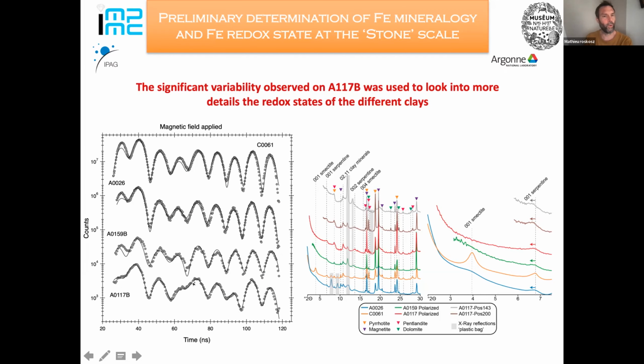And so we were very happy to see that this grain, or this position on this grain, was probably documenting clay minerals with a large amount of serpentine and a very low amount of smectites, which allowed us to look at the redox state of serpentine as compared to smectites, which was a major issue that was hardly tackled by even STXM so far.